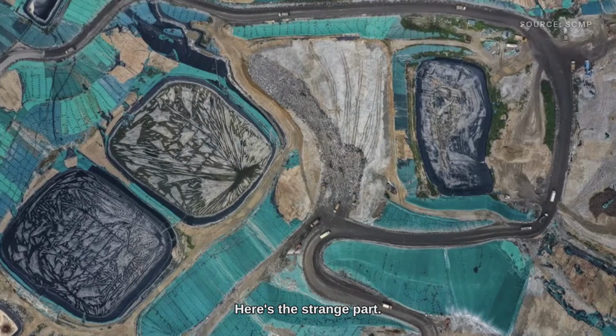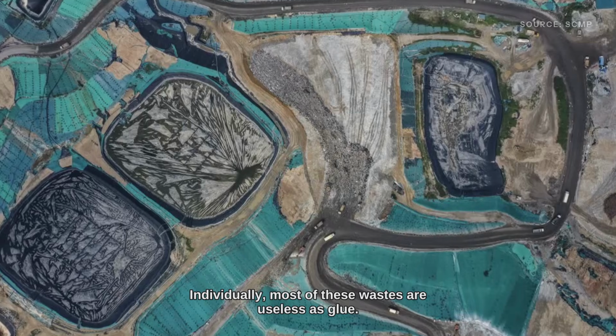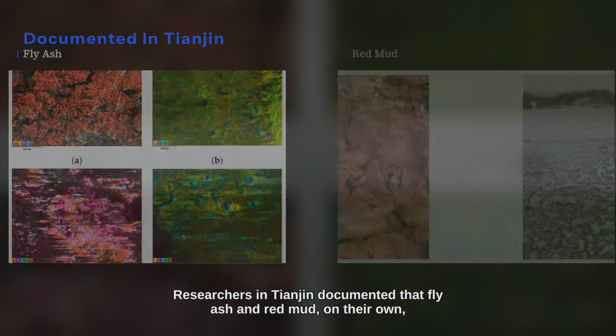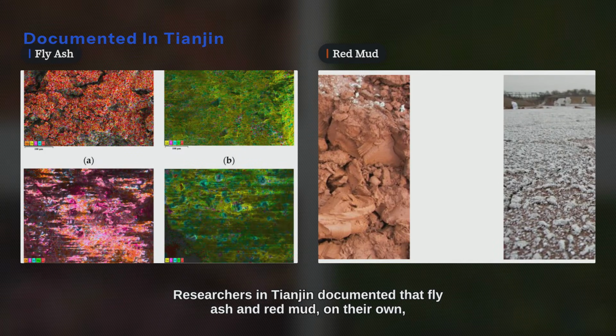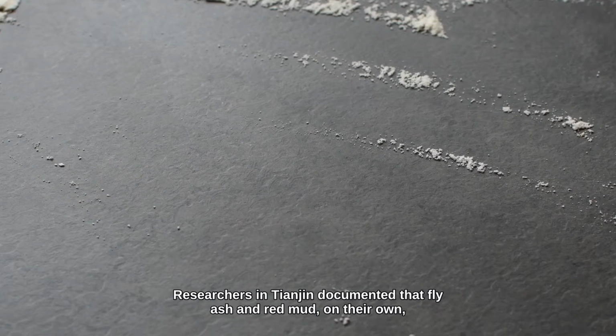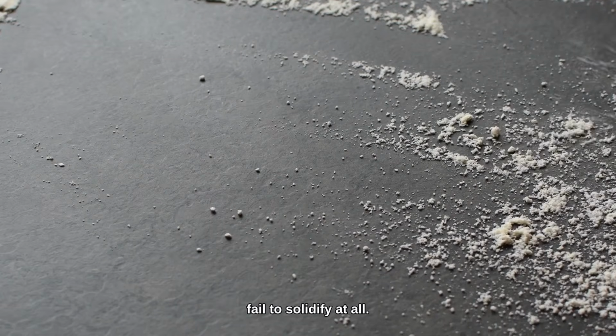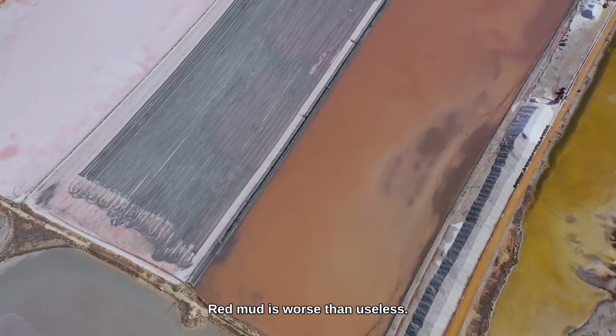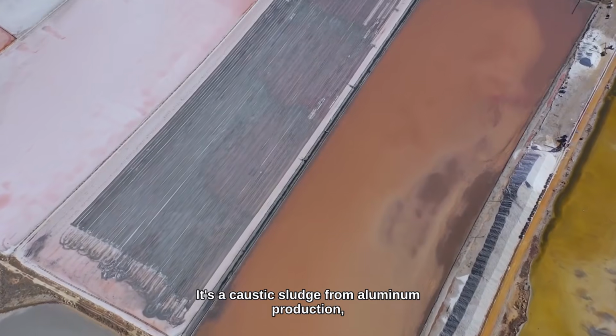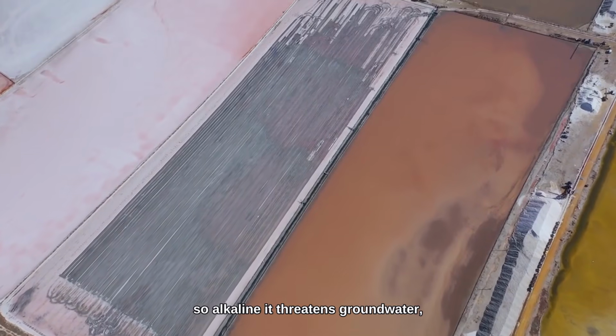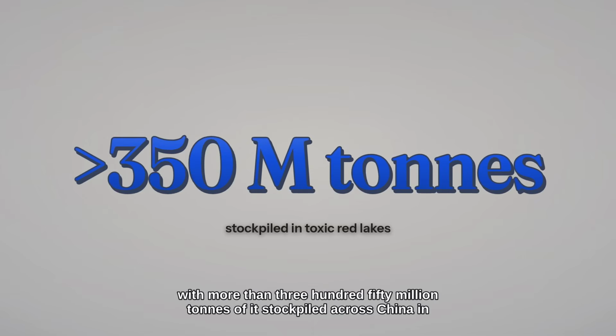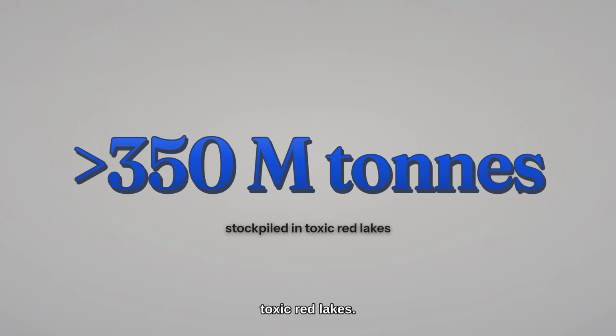Here's the strange part. Individually, most of these wastes are useless as glue. Researchers in Tianjin documented that fly ash and red mud, on their own, fail to solidify at all. Red mud is worse than useless. It's a caustic sludge from aluminum production, so alkaline, it threatens groundwater, with more than 350 million tons of it stockpiled across China in toxic red lakes.